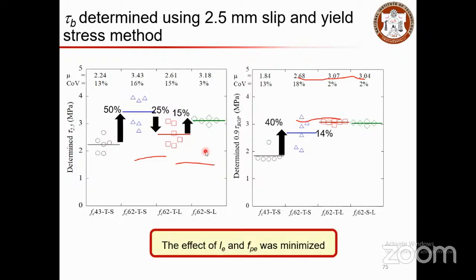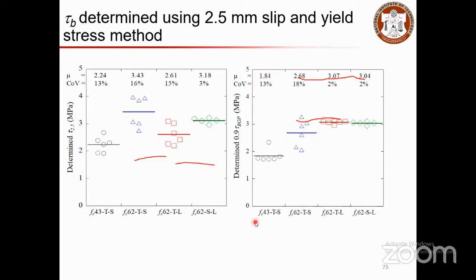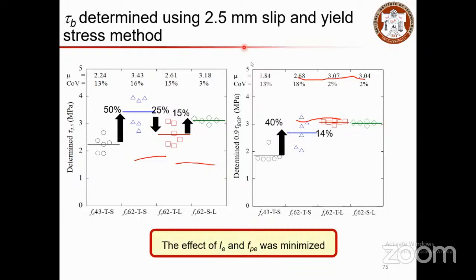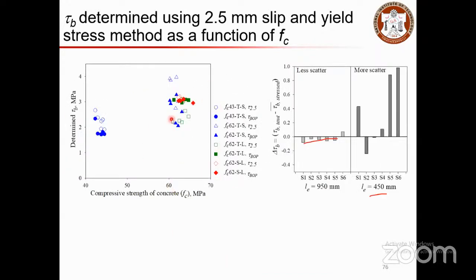So from this, when we consider the effect of embedded length, the defining method is very good. Instead of 2.5 mm slip, you consider the point where the behavior changes. By considering that, we could eliminate the effect of the total embedment length and the effect of pre-stress, so those effects could be minimized. If you look at the bond strength definition using 2.5 mm slip and the yield stress method, they give almost similar results.